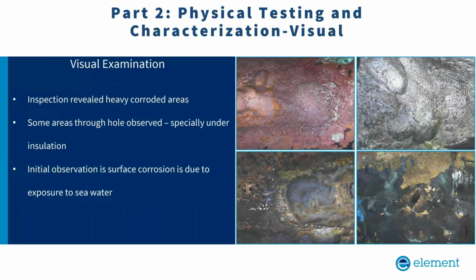The visual examination revealed heavily corroded areas, as you can see in the slide, four different pictures. In some areas, through holes were observed. So the initial observation of the surface concluded that there is mostly surface corrosion, and this could be due to exposure to seawater.